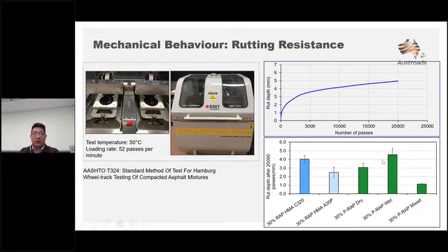So in general, we can see here that the 30% PRAP mixes show an improvement compared to the 30% RAP with C320. It is again the case of 30% PRAP wet, because the PRAP was produced with C320 modified with 2% of plastic. The original results of the C170 asphalt mix, the rut depth was around 9 millimeters. So the result here shows significant improvement in terms of the rut depth for this asphalt mix.